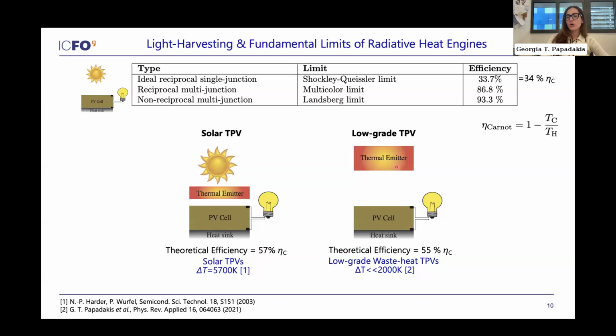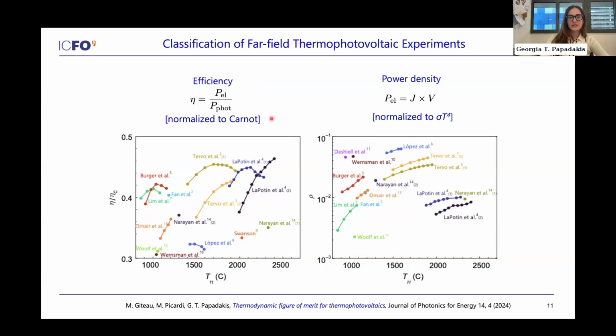And if I work with other types of thermal emitters that are directly heated by some external source, you can get much higher numbers. And there are many interesting topics and physics that you can harness in order to get this very high efficiency. Now, here are some experimental results from recent years. So this is where the Shockley-Queisser limit is. And you can see here that many experimental papers have already surpassed the Shockley-Queisser limit in TPVs, where the efficiency is defined by the electrical power density that is extracted out of the cell divided by the photonic heat exchange between the emitter and the cell.